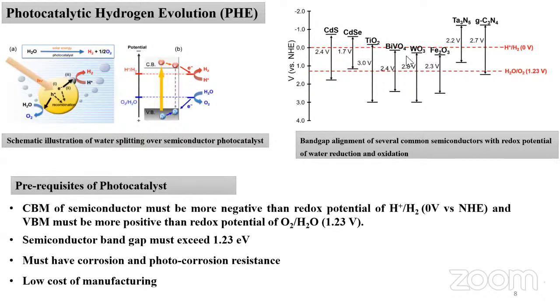water oxidation to O2. So here you can see some of the photocatalysts shown with their band edge positions. Typically you can see TiO2. We have already seen the other advantages of TiO2 as a best photocatalyst: it is photostable, photoactive, inexpensive, environmentally friendly, and so many things. And the band edge positions are properly arranged. As we have seen, the conduction band of the semiconductor must be more negative than the redox potential of H plus to H2. So you can see that the band edge positions are proper here, and some other semiconductors are also there.